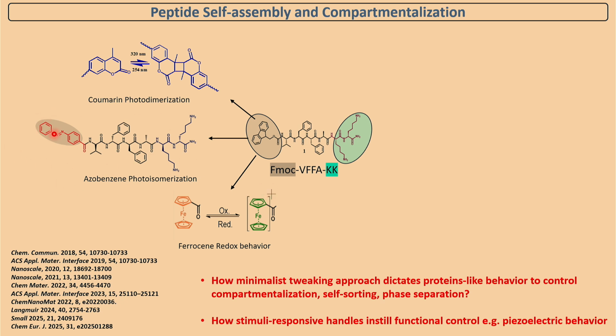Another interesting thing, this is where actually our photo things will start, is this azobenzene we put, and all of you know azobenzene can have very nice cis-trans isomerization, right? Incidentally, this is in trans form. If you shine UV light, 365 nanometer light, this will go into the cis form or Z form. And again, if you irradiate that with 405 visible light, it comes back into this. So we wanted to look at how the self-assembly is for this.